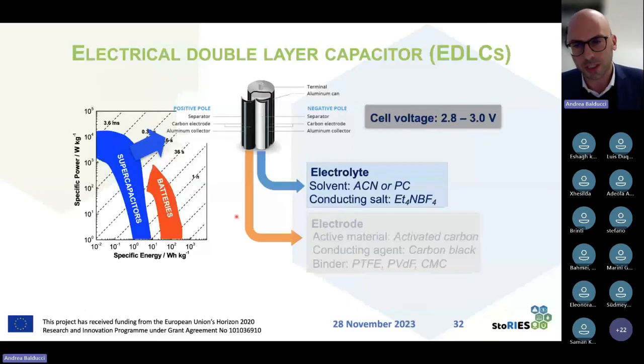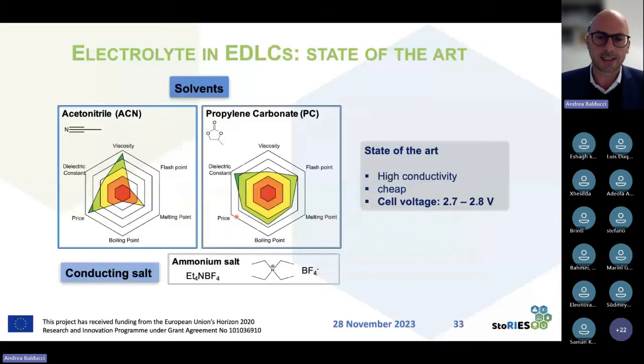As we said, to do this, of course, we need to introduce an electrolyte. And the electrolyte, as we already mentioned before, is a key component because basically the electrolyte is determining the cell voltage. And nowadays, as electrolyte, we are using a mixture of a salt, which is typically an ammonium salt, like this tetraethylammonium tetrafluoroborate. Why is this salt used?